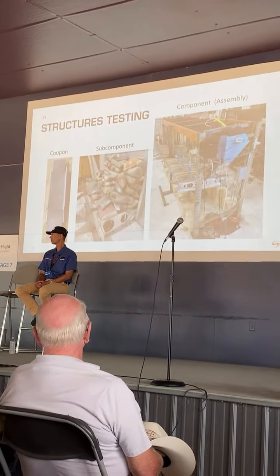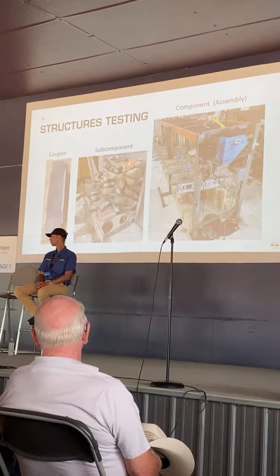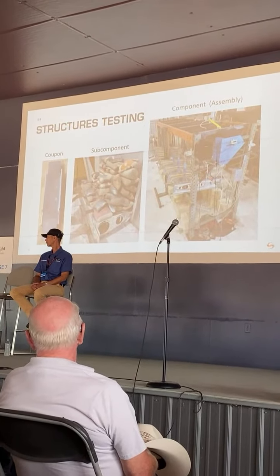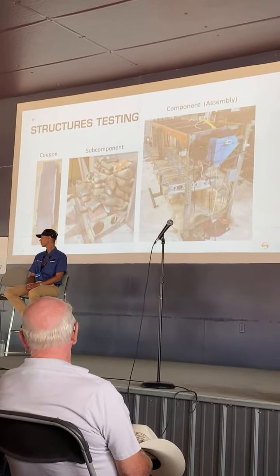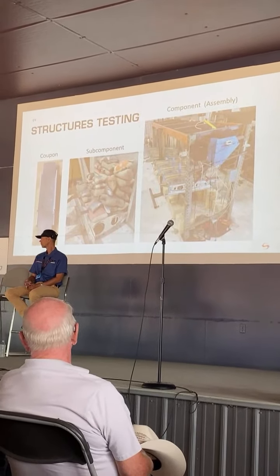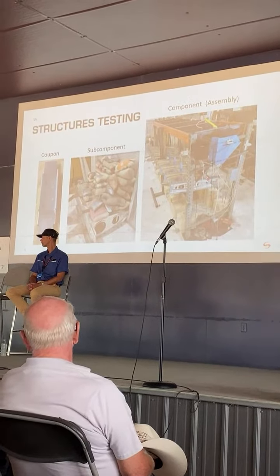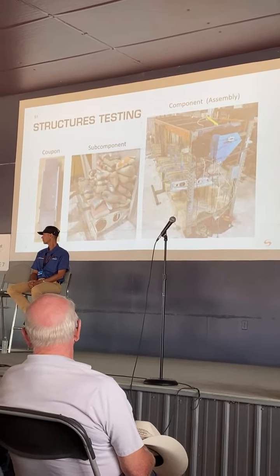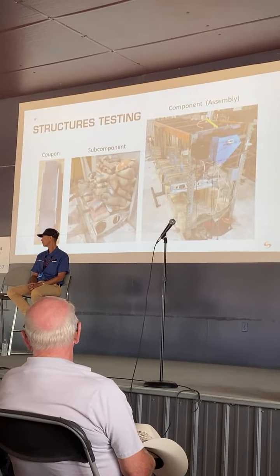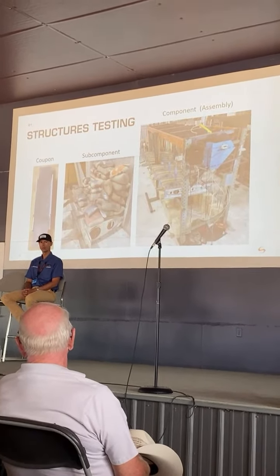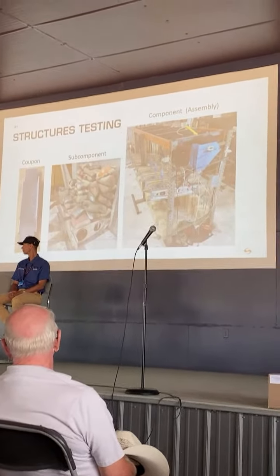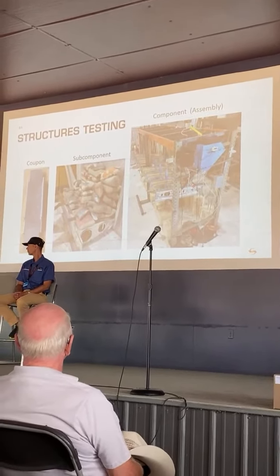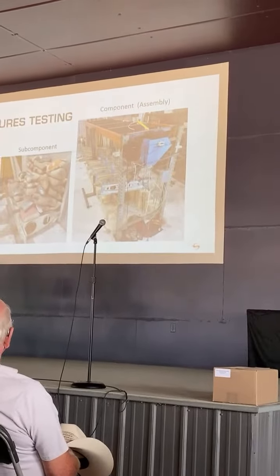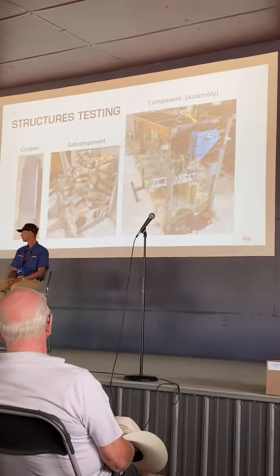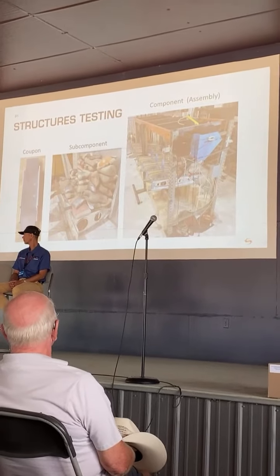Here are some examples of that here at Van's. There's a coupon on the left, and then in the center, you see a D-cell loaded up that's about 250 pounds per rib. That's indicative of a limit pull-up load on that D-cell, and we're testing what happens to those ribs with different types of failures. We also tested it beyond ultimate, and we'll show that in a bit. And then on the right is component assembly testing, and I'll get back to that in a minute. That's the RV-12 stabilator, and we're testing that to limit numerous times.